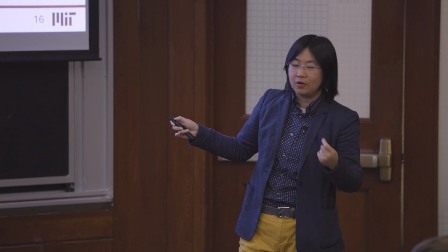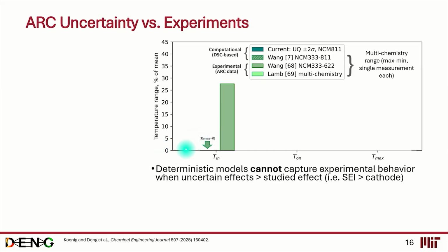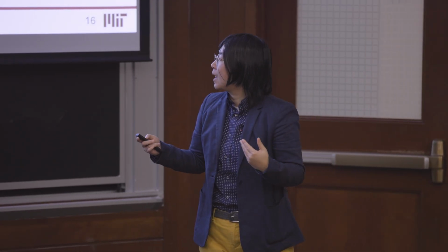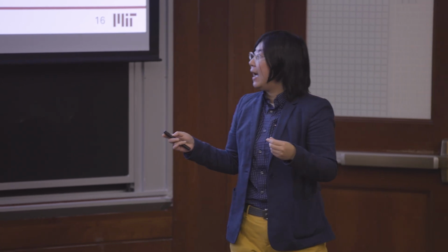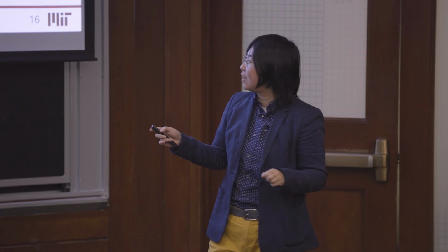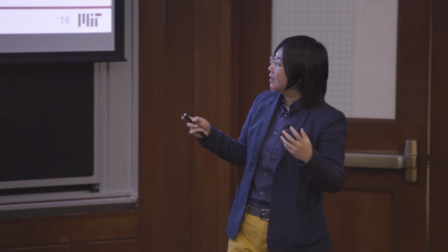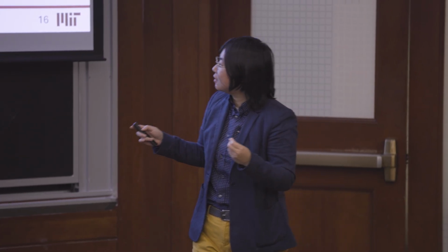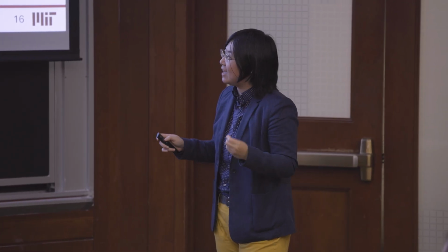And to highlight the importance of considering all the uncertainties associated with single components, for example, now you see this is an experimental measurement, done across different chemistries. Basically, this experiment shows that the onset of a thermal runaway depends on the cathode chemistry. However, if you recall the figure I just showed you, at this relatively low temperature, roughly 80 Celsius, you shouldn't have any dependence on the cathode. It's purely determined by the SEI layer.